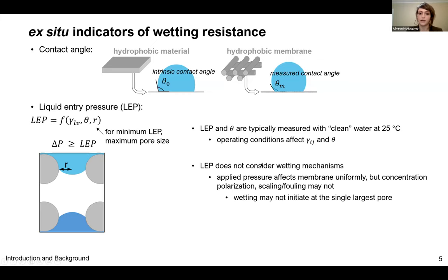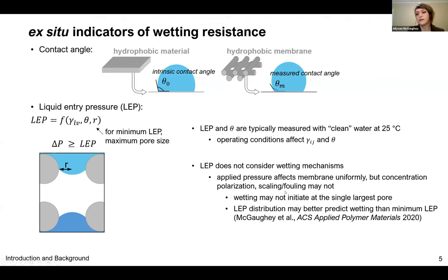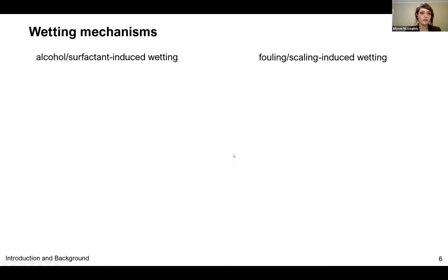In these cases, wetting may not initiate at the largest pore, the maximum pore size, but instead where scaling or fouling is most severe. In a previous study, we introduced the LEP distribution based on the pore size distribution to better predict wetting. But these ex situ metrics have limitations and they may not accurately describe wetting that occurs in situ. The mechanisms that are most relevant to MD